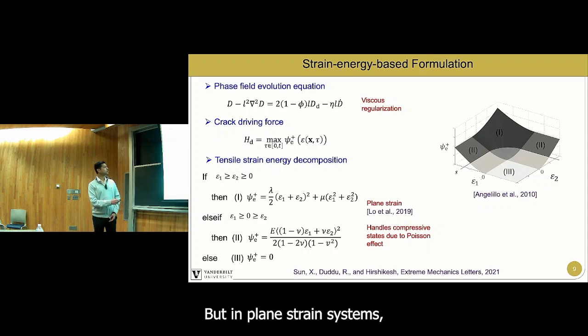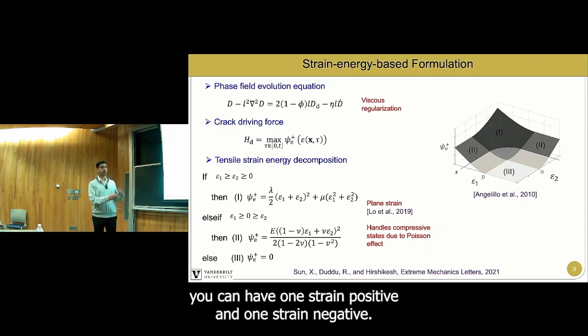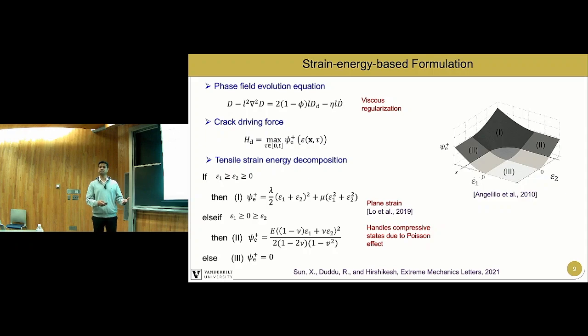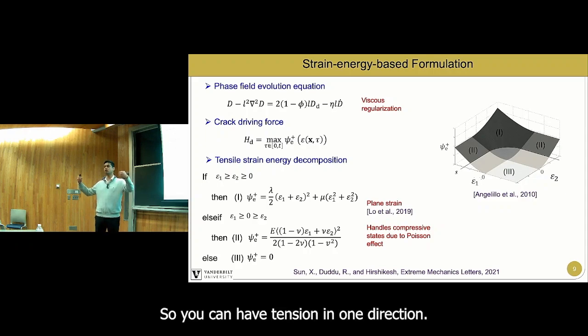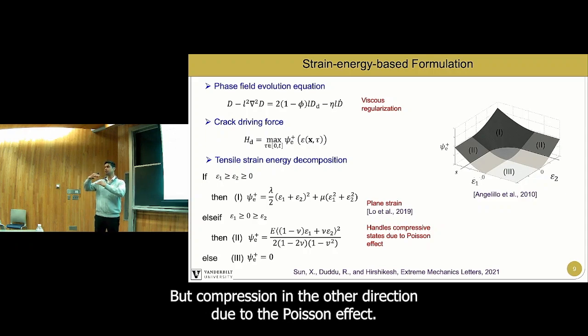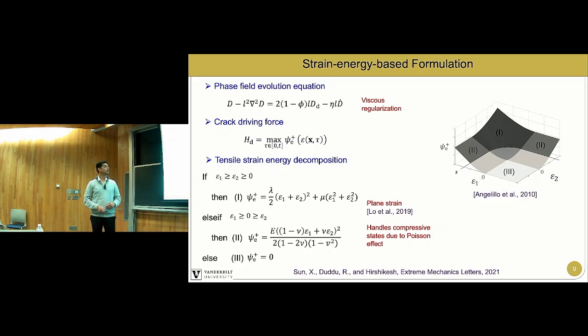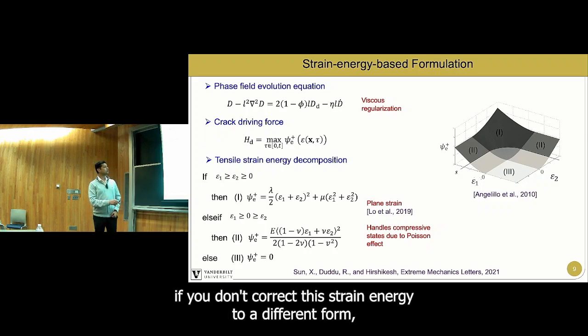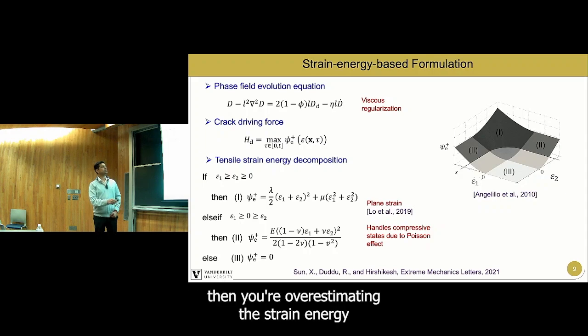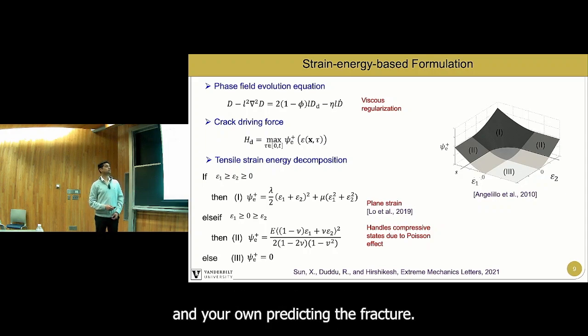But in plane strain systems, you can have one strain positive and one strain negative, right? So you can have tension in one direction, but compression in the other direction due to the Poisson effect. And when that happens, if you don't correct this strain energy to a different form, then you're overestimating the strain energy and you're over-predicting the fracture.